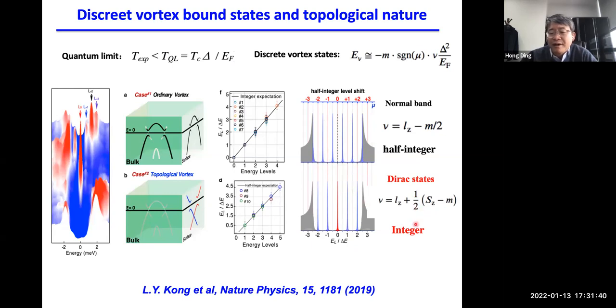So you will have an integer. In this case, you have a zero mode, you have plus or minus one, plus or minus two. Since in this material some of the vortices are ordinary and some are topological, we see both cases. We see the half-integer case, and also the integer case, and it's shown here.